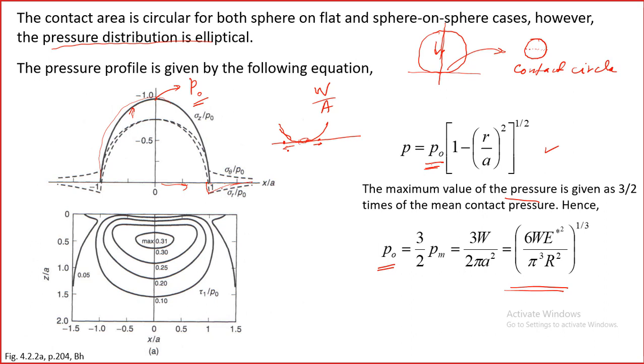And this gives the profile of the shear stress. So shear stress divided by P naught, where P naught is the maximum pressure. So it has been normalized, and you can see that the maximum shear stress happens here at this point, 0.3 times P naught basically. And the distance from the center of the contact circle is around 0.5 z over a.